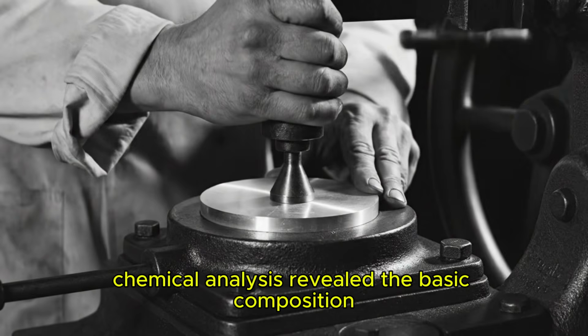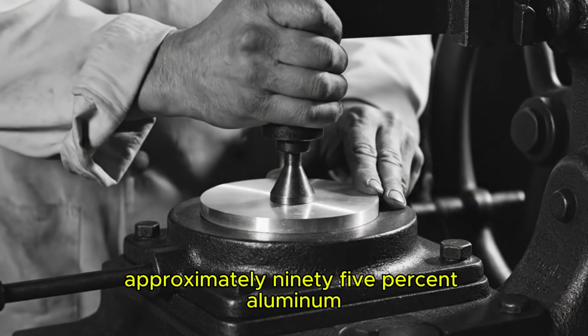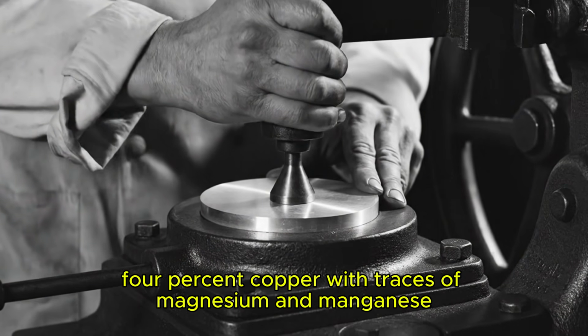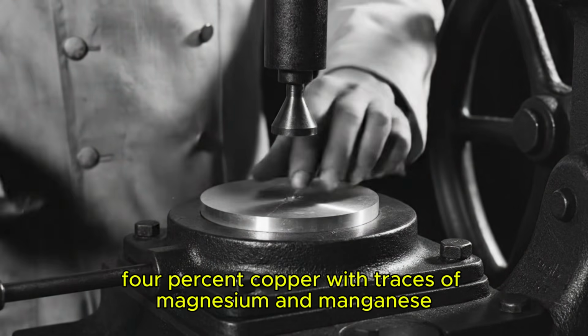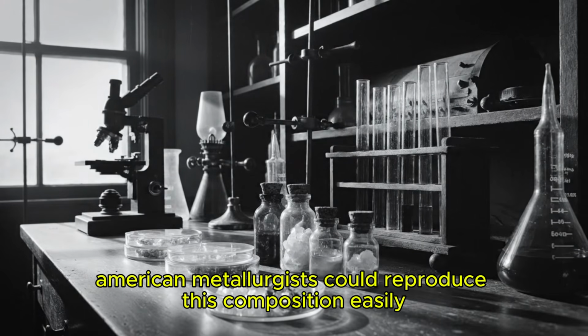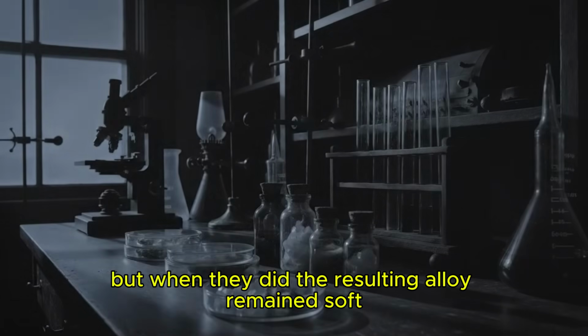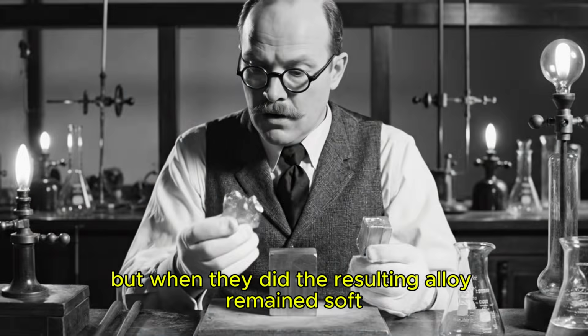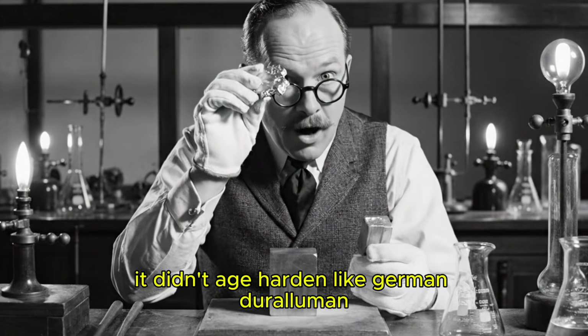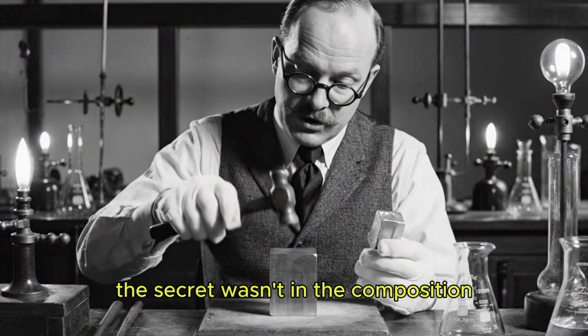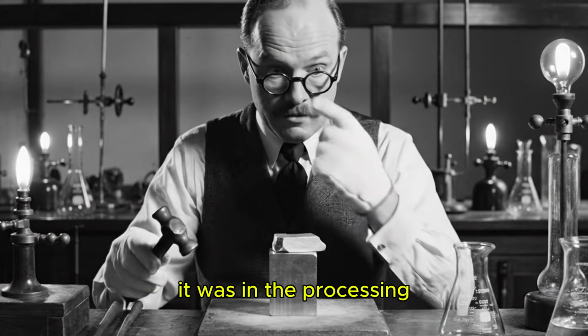Chemical analysis revealed the basic composition: approximately 95% aluminum, 4% copper, with traces of magnesium and manganese. American metallurgists could reproduce this composition easily, but when they did, the resulting alloy remained soft. It didn't age harden like German duralumin. The secret wasn't in the composition, it was in the processing.